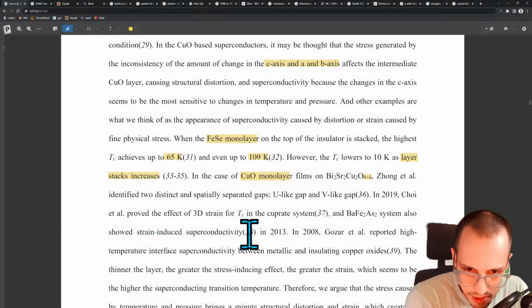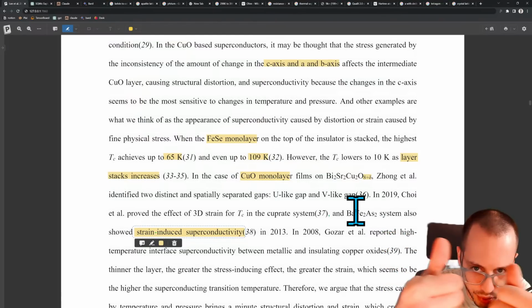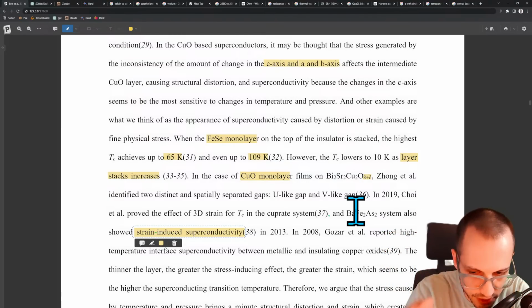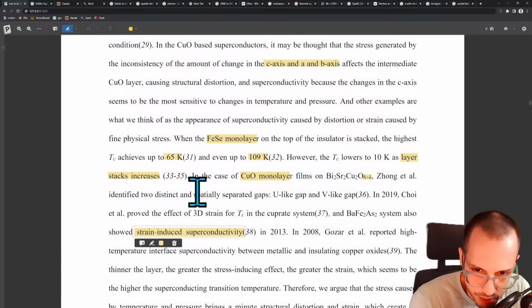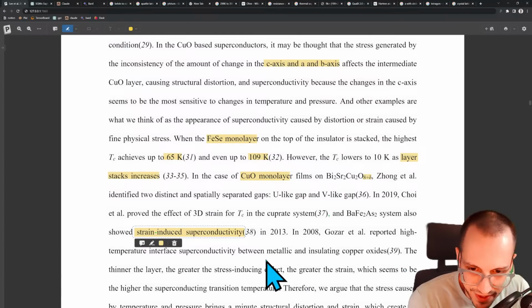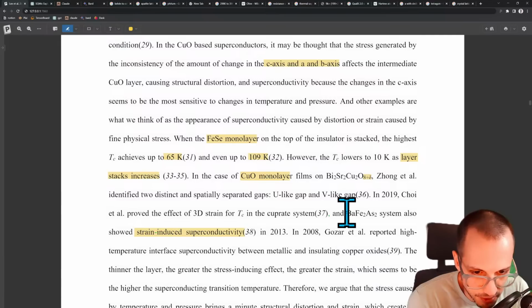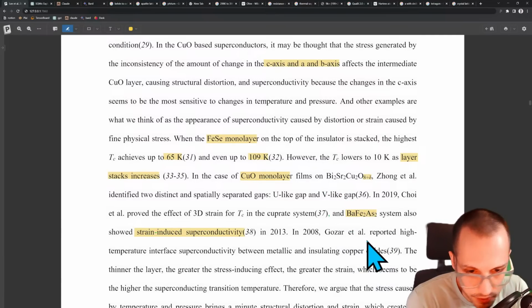Identified two distinct and spatially separated gaps, U-like gaps and V-like gaps. Prove the effect of 3D strain from the TC in the cuprate system. BaFe2As2 system also showed strain-induced superconductivity. So strain is whenever you take a metal and you basically like pulling it, right? Pulling it, maybe shearing it. So it seems like people have been making superconductors by applying strain to the metals, right? So it seems like these FeSe and CuO are based on temperature, and then you have a different type of superconductors that people have been working on that are based on strain, and these are the weird BaFe2As2.